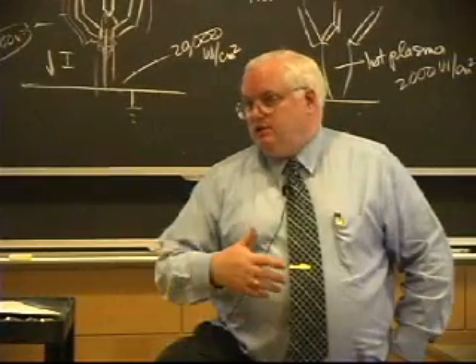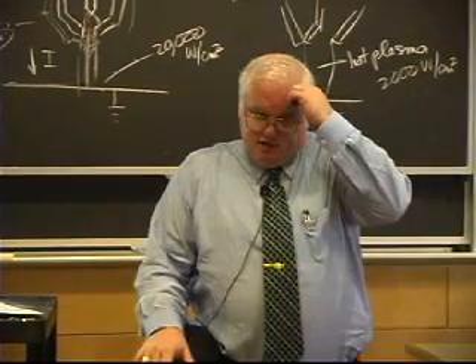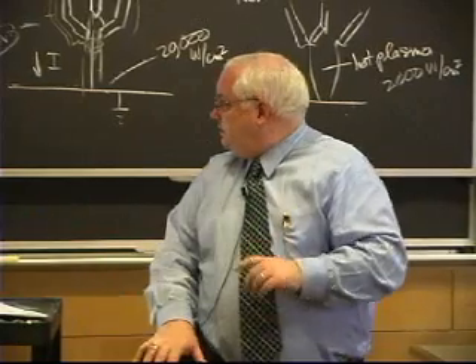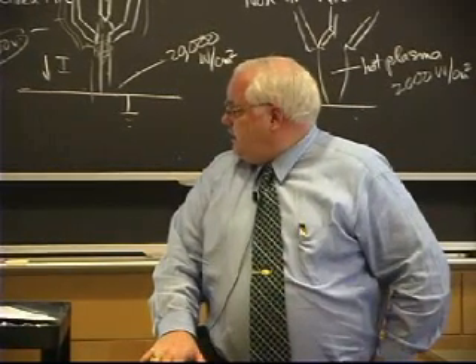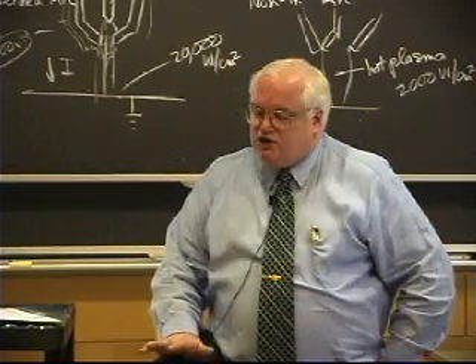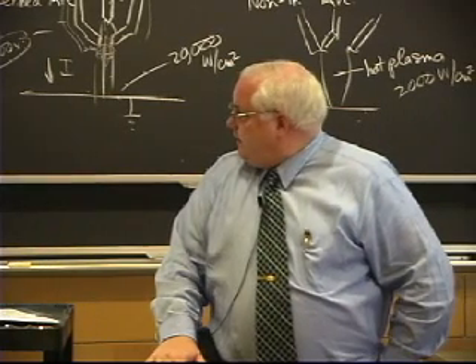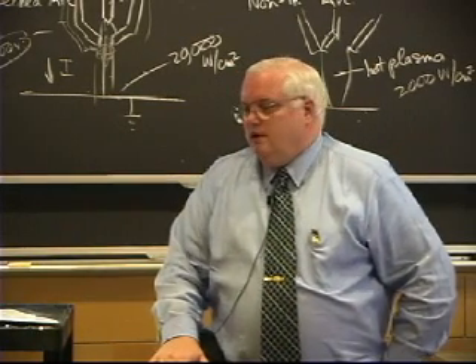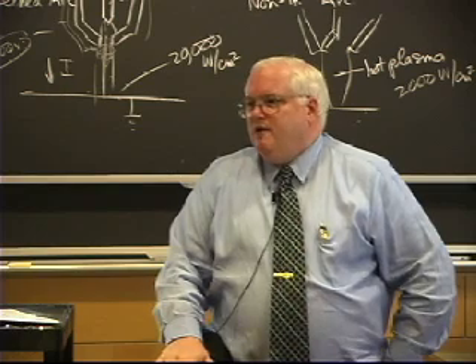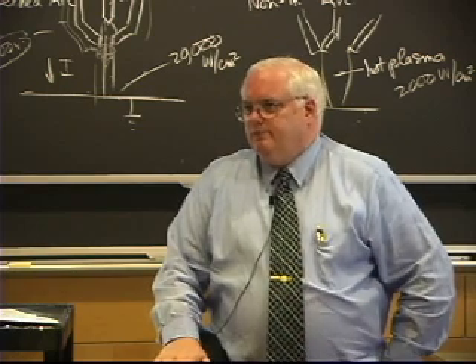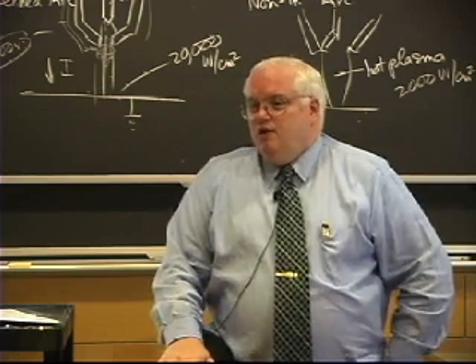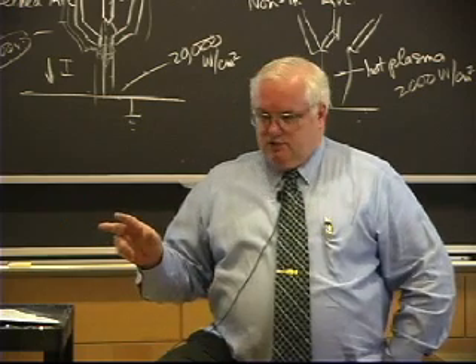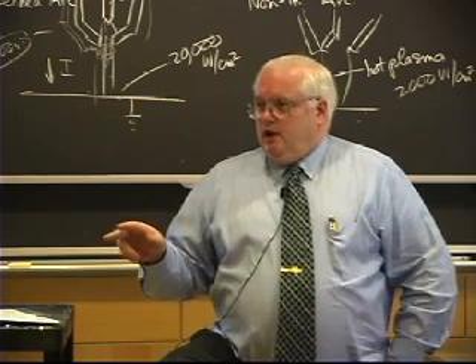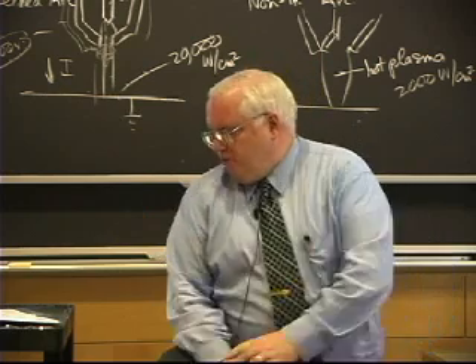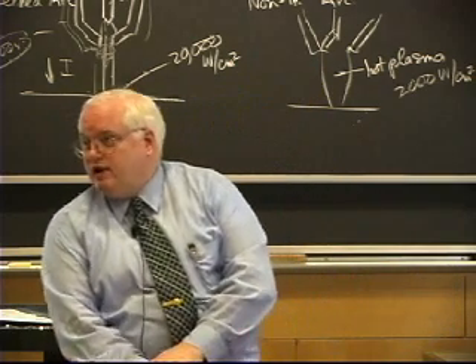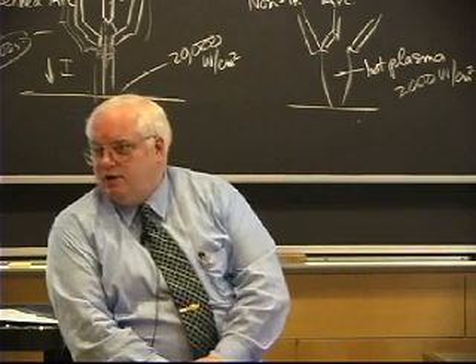That's the theory, and that's all the theory anybody knows, but it turns out if you try to do this type, if you change the polarity and you're welding on aluminum in a very, very, very dry environment or without oxygen, you will find that it doesn't matter what your polarity is, you will not get the cleaning action. And the person who learned this, and we've never published it, was actually Lieutenant Commander Dan Reese doing his thesis on welding of titanium in 1983.